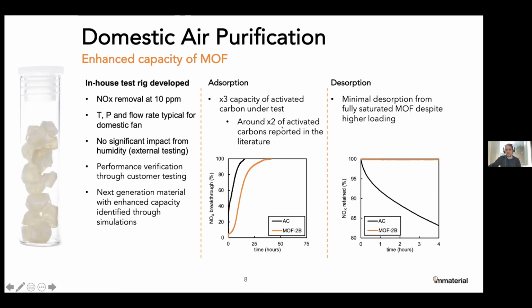Well, you can see there's also this note here: when we look in the literature, we believe that's around twice the capacity of any activated carbon we can find, but it's much harder to make those comparisons because of all the changes in conditions. But we certainly think that we've got enhanced capacity versus the incumbent technology of activated carbons in this application. That's very important. Possibly even more important is when you look at desorption.